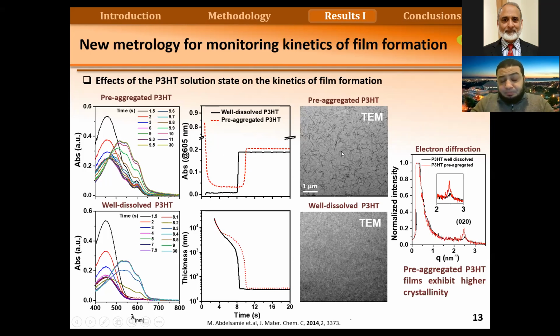We can see here the formation of fibrils for the pre-aggregated one, but we don't have fibrils in the well-dissolved one. And we can also see a higher crystallinity. If we make transistors from these, we get very high mobility for the pre-aggregated one. I think because of these fibrils, it's highly crystalline, and they can improve the electron and hole movement during the film. So with the pre-aggregation of the solution, we can get a much better product at the end.